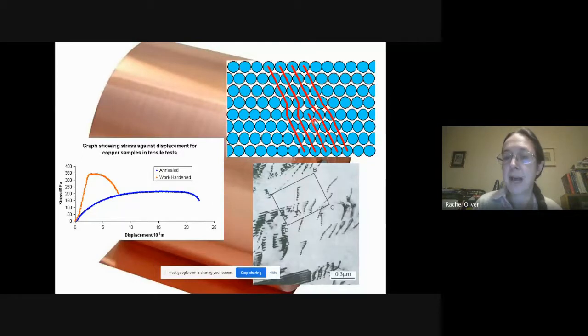That extra sheet of atoms, I would call it an extra half plane of atoms, is what's distorting the bonding around it. And the edge of that extra sheet of atoms would run into my slide, into the page, creating a line through the crystal where the bonding is disturbed and distorted. And that is a line defect that we refer to as a dislocation. You can see those lines here, indeed in copper, in a transmission electron microscopy image. And these defects in copper and in other metals are now really quite well understood.